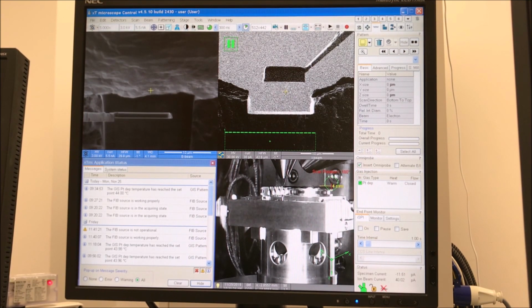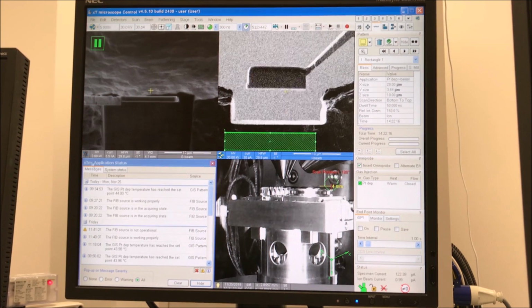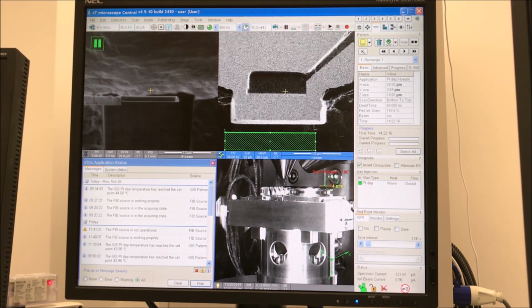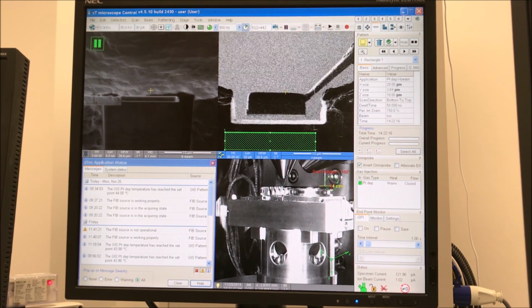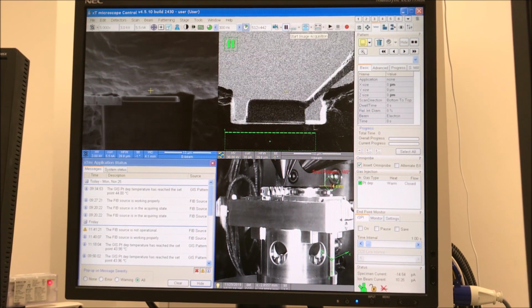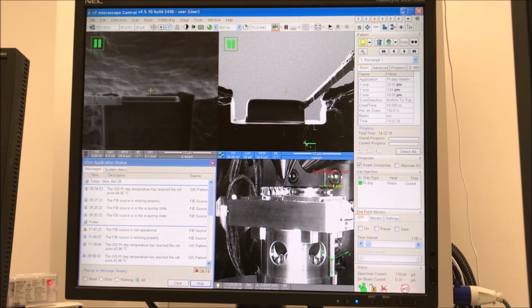Otherwise, you're going to end up with part of the shelf blocking the lamella when you do TEM, and you obviously don't want that. So you don't have to have the lamella in contact with the shelf. It can be really close, but not perfectly in contact, but we actually do have light contact here.